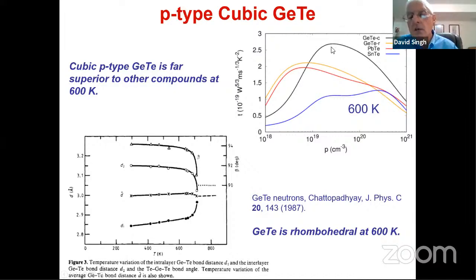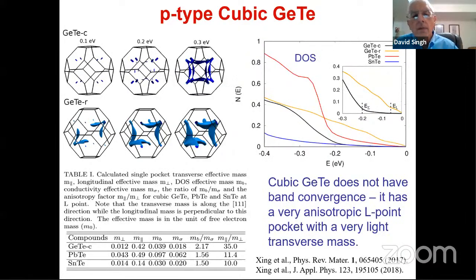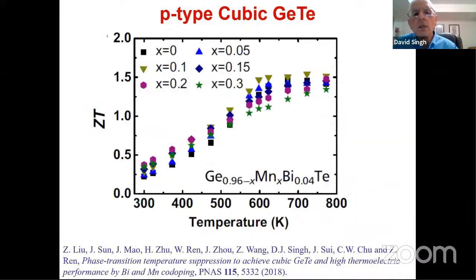So we discussed that with experimental colleagues, and we discussed the reasons. I'm not going to discuss them, but they did it. They alloyed some manganese, and they found out that manganese can make it cubic. It also makes a lot of scattering, but still the ZT is very high. So they found a material with a high ZT over a wide temperature range by making germanium telluride cubic.